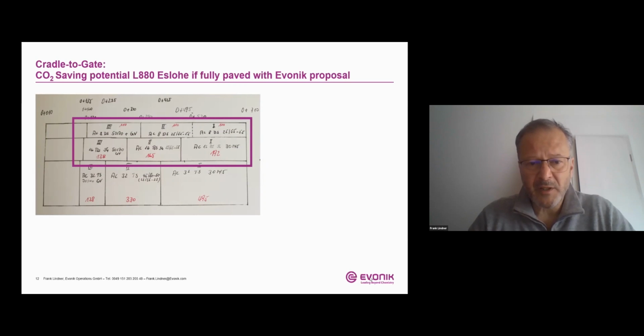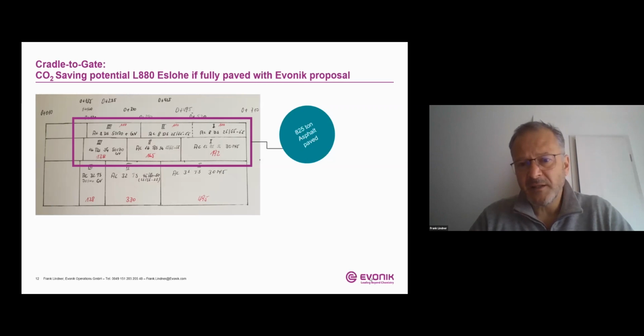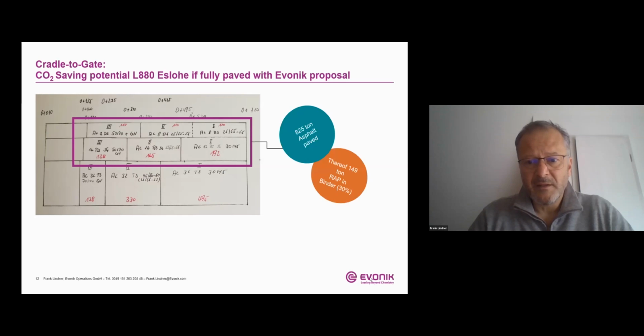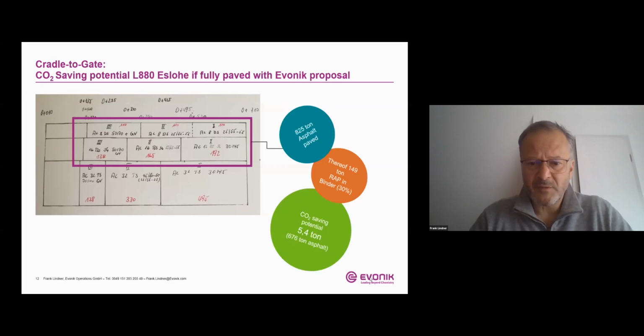Let's make a calculation based on the small project which we used for the testings. This is the setup, and in total for the top layer and binder layer, 825 tons of asphalt have been produced and paved. There was 30% recycling asphalt in the binder layer, which we have to extract from the calculation. So pure asphalt was roughly 676 tons.